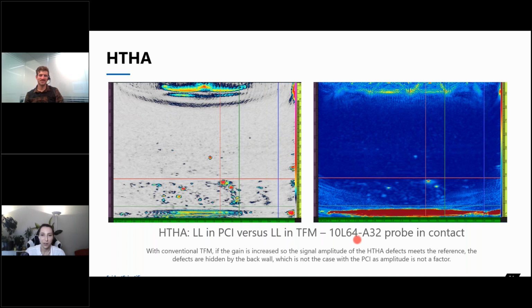All right, so here on the right with the blue background, we see the conventional TFM. We use the 10L64 A32 probe directly in contact. This is also HTHA, as we saw earlier as well. And on the left here, we have the PCI with the white background. And so as we can see, we can still detect a little bit here with the TFM. We see that something's happening, but the signal to noise ratio is definitely not as good as what we have here with the PCI, where we see the cluster or the little cloud of indications that are starting to connect together on this particular one with the PCI.